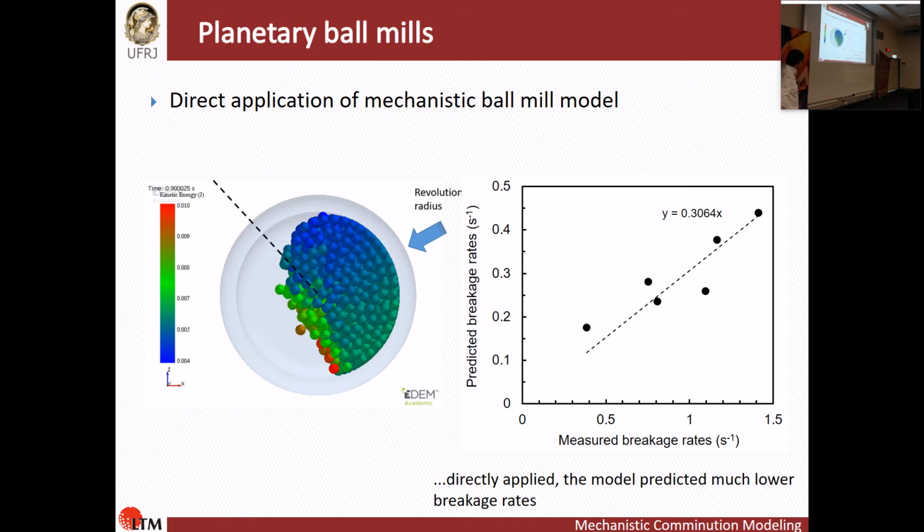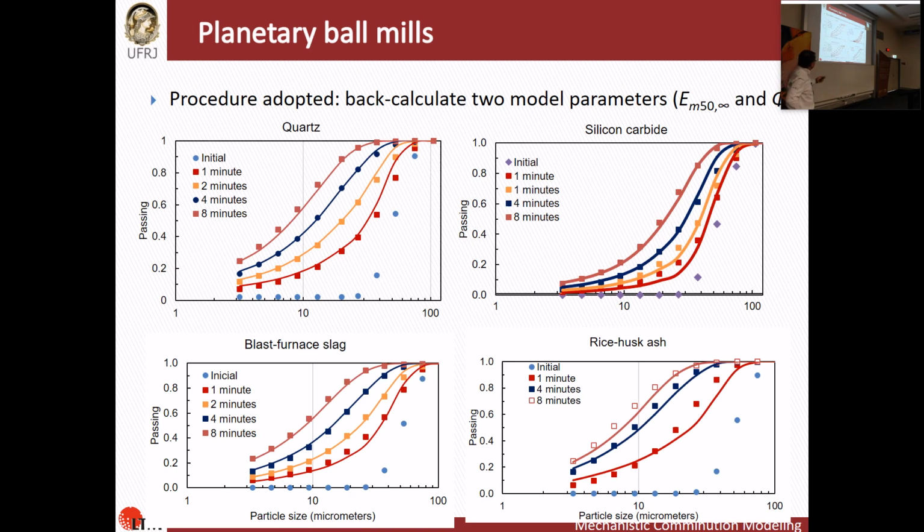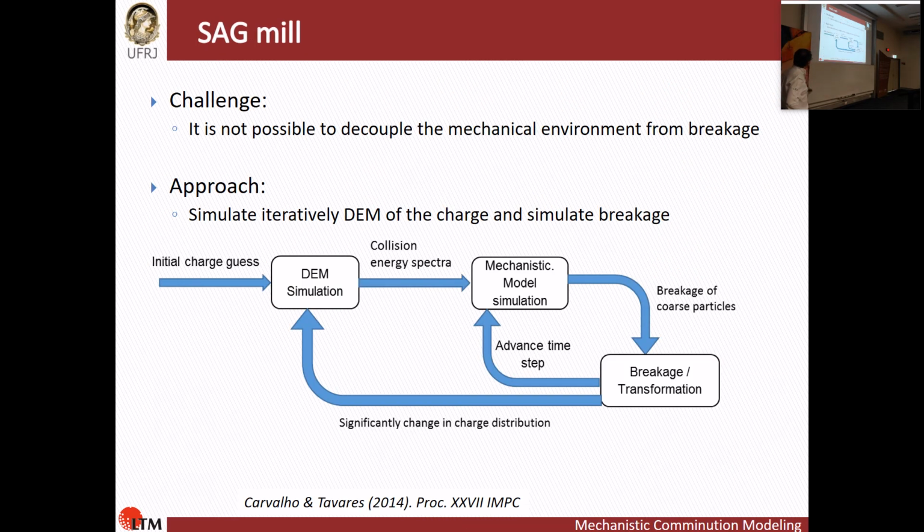It makes sense. And if by any chance we forget about those very difficult tests and just take the model that has 12 parameters, with just 2 parameters fitted from the test, you could calibrate for all different materials and size distributions. For a population balance model, you need at least 7 or 8 parameters to do the same job. So it is quite promising even for this.